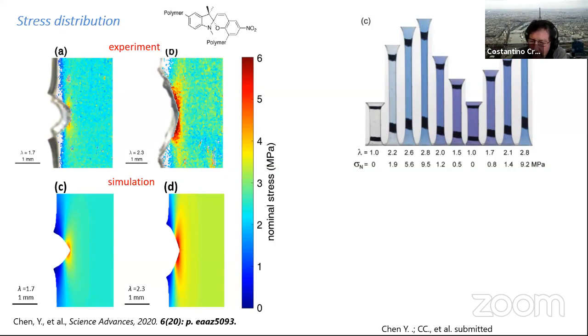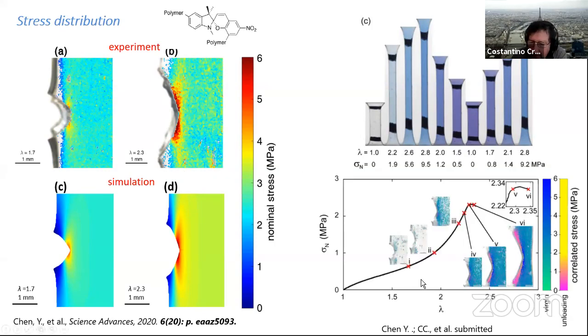So I'm showing here just an image that shows in which way this is different. If you actually look at the propagating crack, so the crack now is moving, the region that you can see recolored in purple is a region that has been loaded and now is being unloaded. So when you detect a color which corresponds to unloading, you know that the crack has actually moved. Now, if you look at the sample when it's completely broken, I'm not going to show you images here, from the color purple you can actually understand how much stress was there as a function of position.